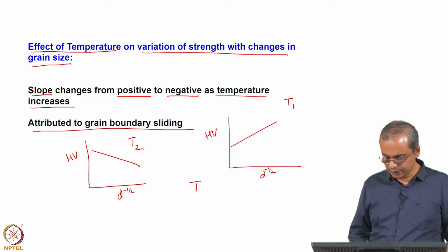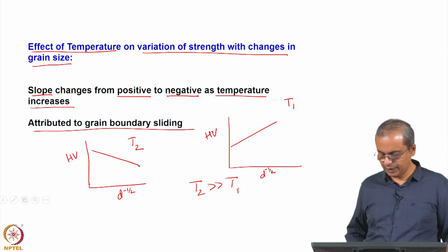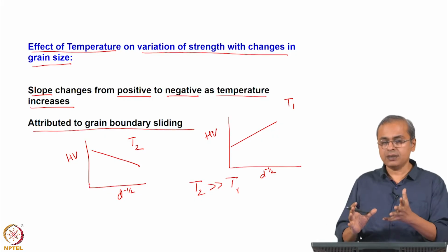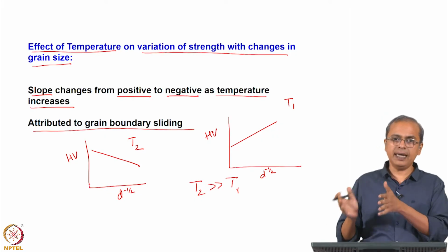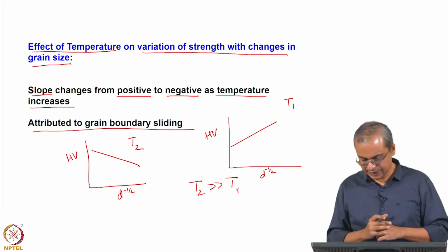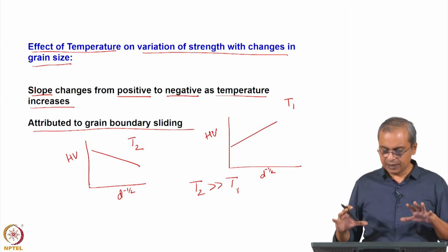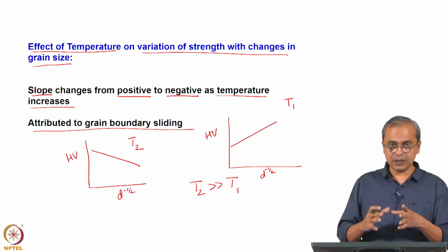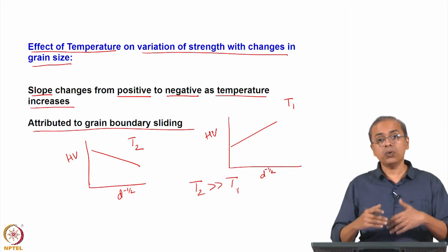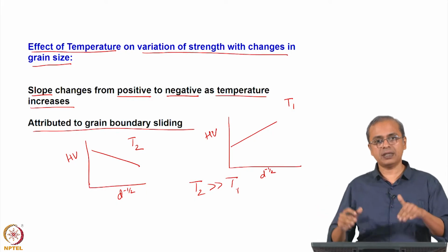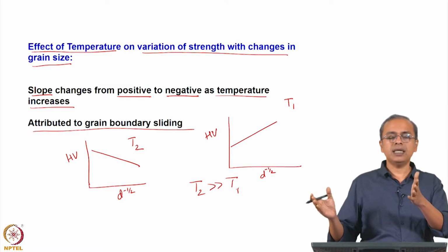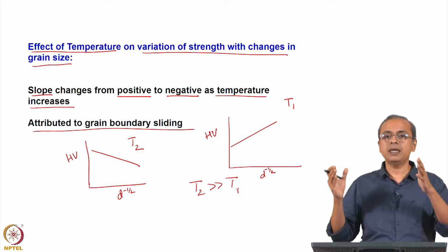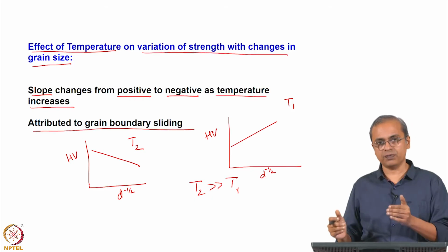And where T2 is significantly greater than T1, you see that this relationship has changed. So, temperature effects on the relative strengths of grain and grain boundary have been investigated to differing degrees, and these kinds of phenomena have been seen before. But what has been observed is that when you go to the nanoscale, you do not have to go to high temperatures. At room temperature, at the same temperature, you see a behavior where at larger grain sizes it follows the Hall Petch relationship, and at very small grain size it shows the inverse of the Hall Petch relationship.